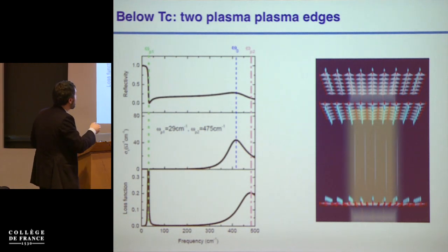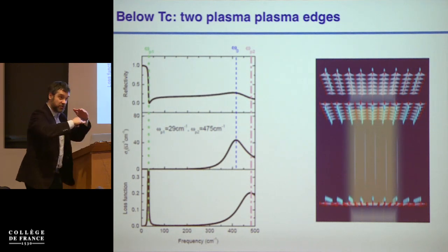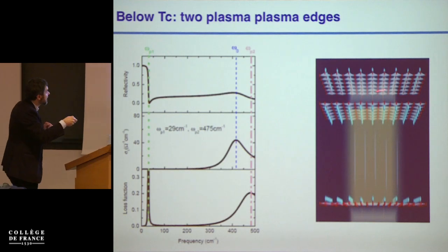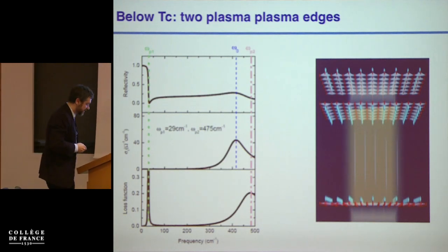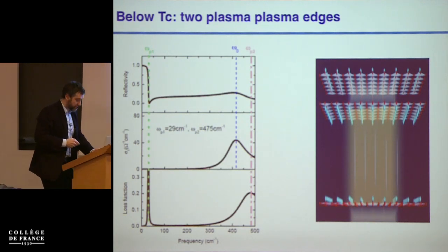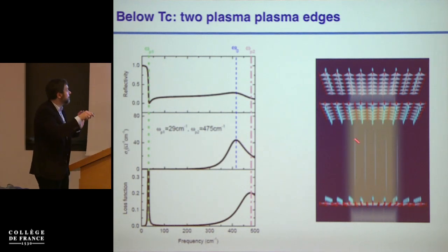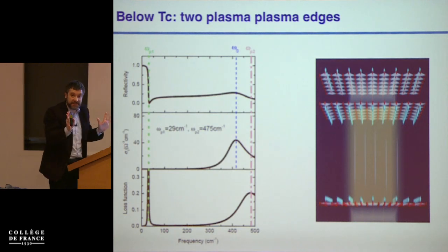This is a broader edge, and this edge is related to tunneling between these closer spaced junctions, and this is at higher frequencies because the tunneling is stronger. Okay, so now what we're going to do is we're going to pump the apical oxygen in between, and we're going to look at the features related to this low frequency edge, which is very sharp and very clearly defined, and is usually at equilibrium, is there only when the superconducting state is there.